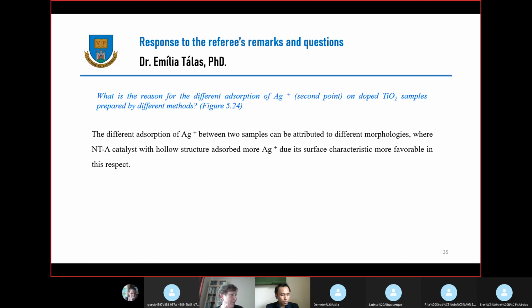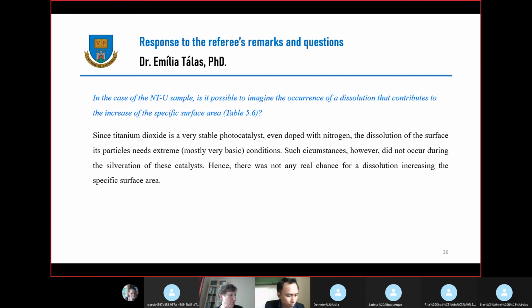That was the question: can you imagine any kind of dissolution which contributes to the increase of the specific surface area? In this case, because titanium dioxide is a very chemically stable material, even after nitrogen doping, dissolution on the surface needs to be in extreme conditions, maybe, mostly in these cases.